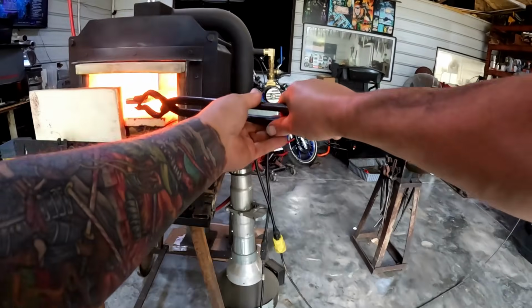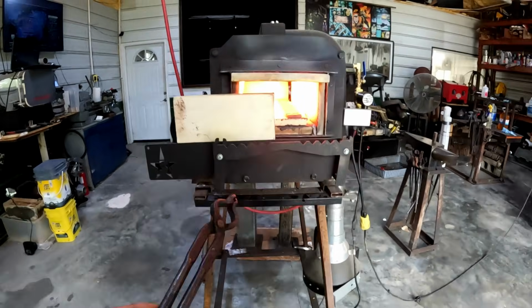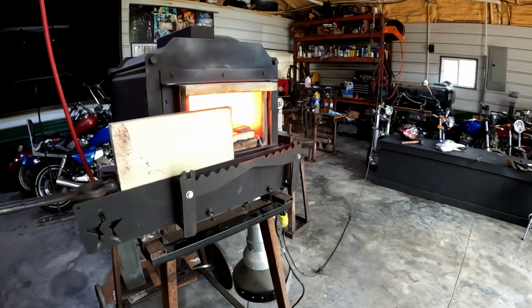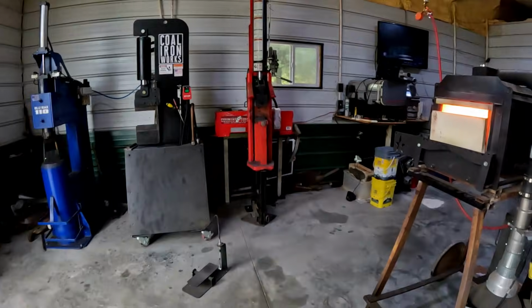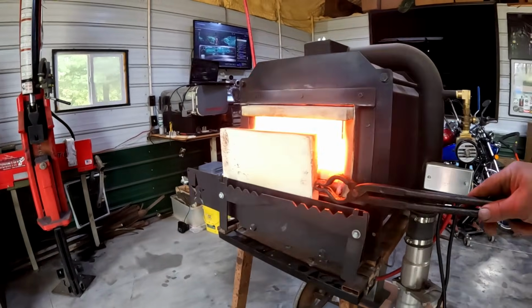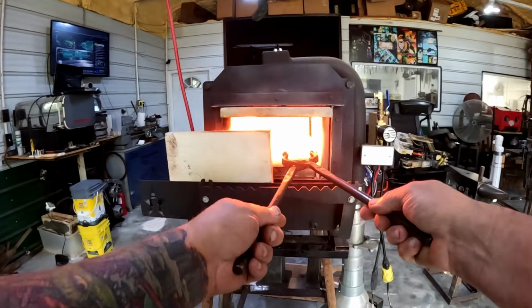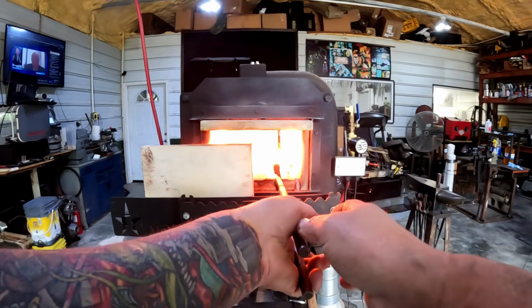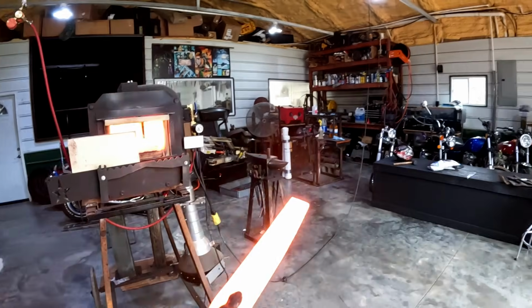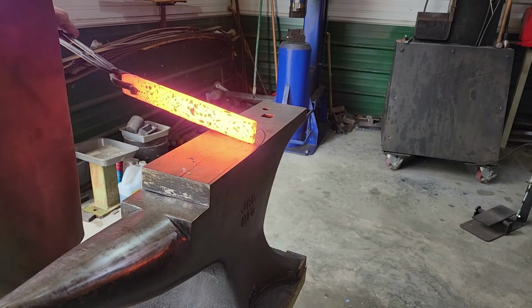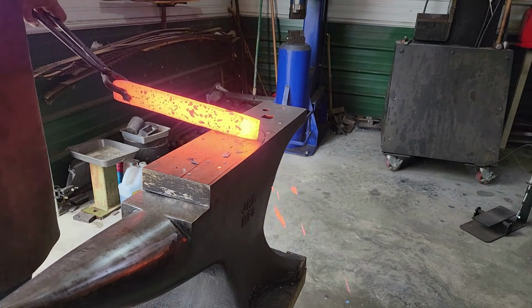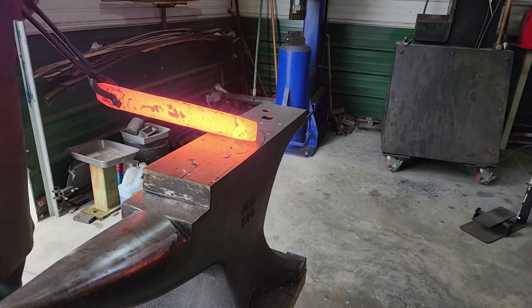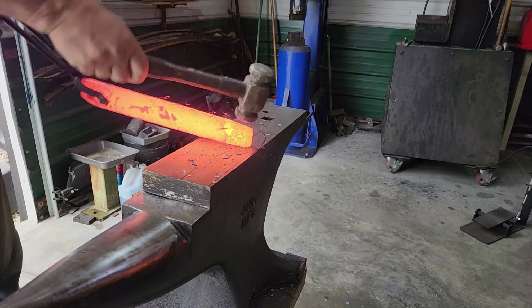Once it's square and behaving, we open the throttle, but not redline. Still gotta babysit the speed. Why? Even welded tight, mosaic layers can delaminate if you hammer like you're mad at your ex. Too fast, too hard, and you'll get cracks that sneak up later like a tax audit. Slow and steady keeps the pattern crisp and the blade alive.